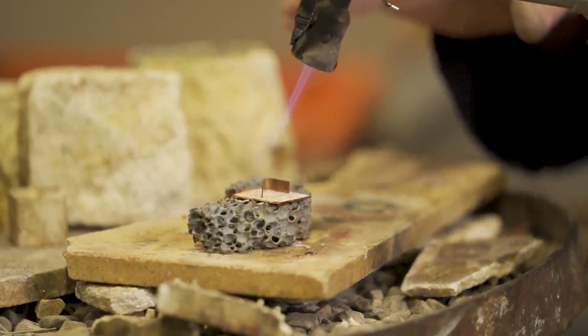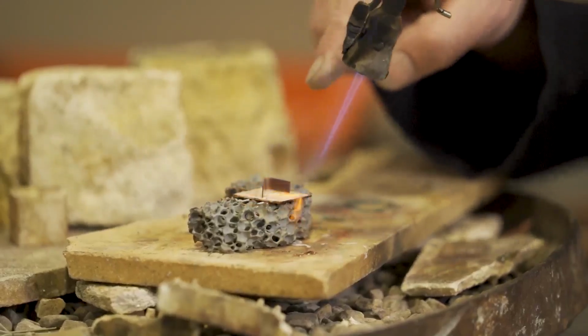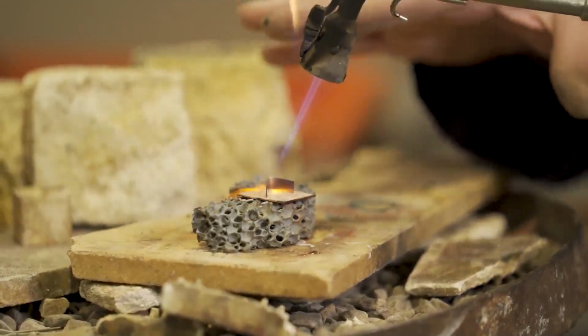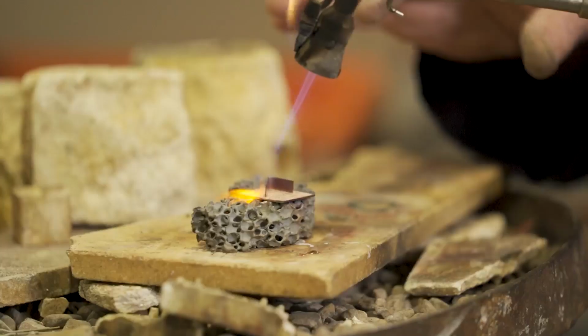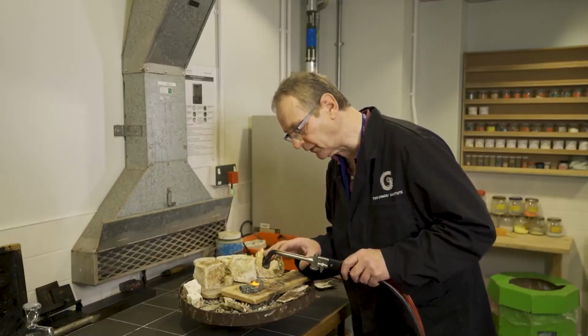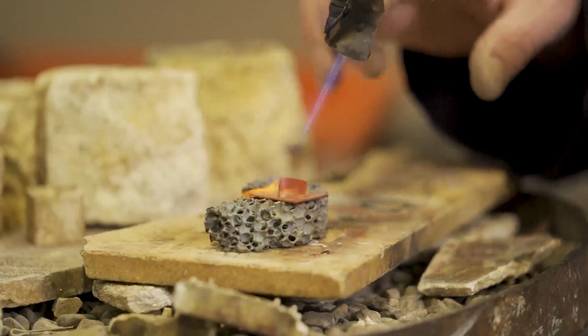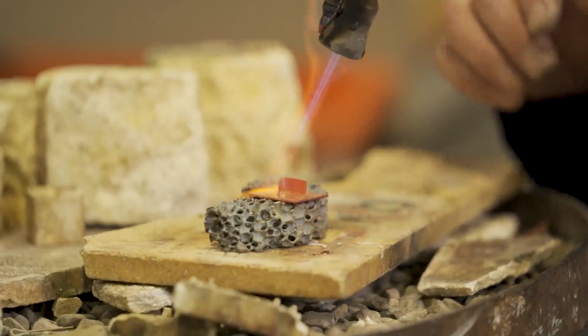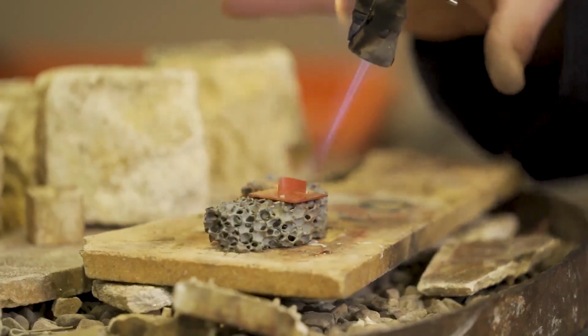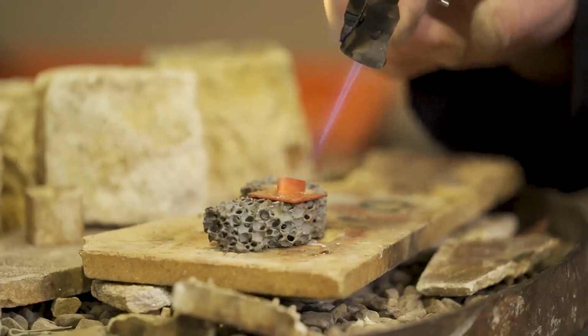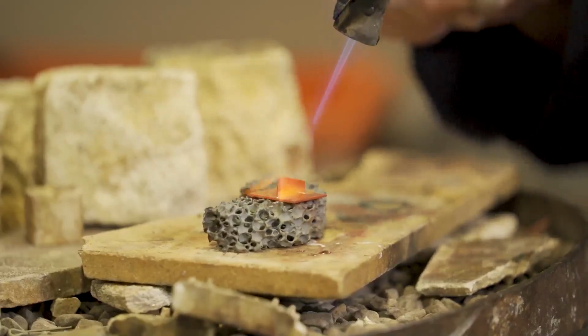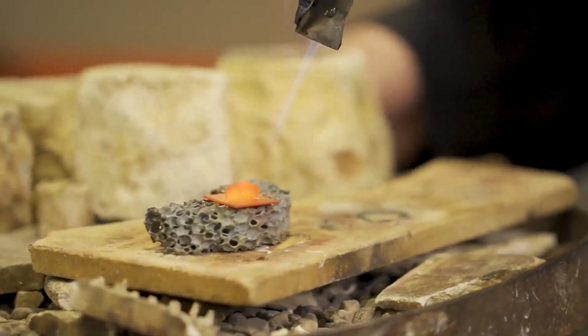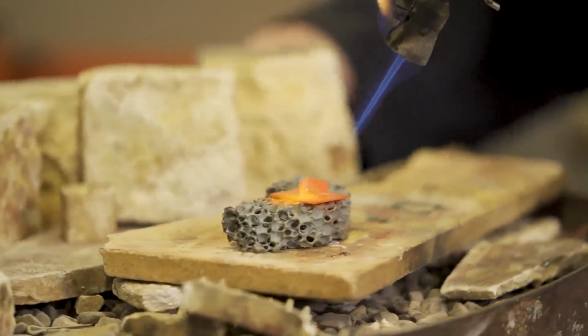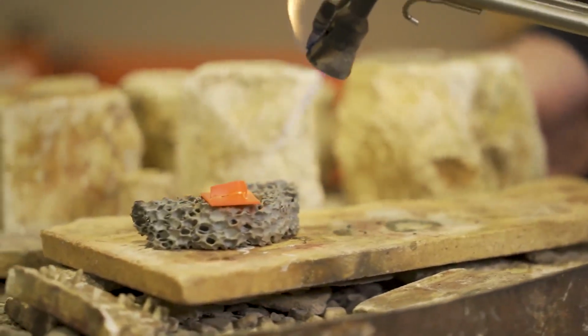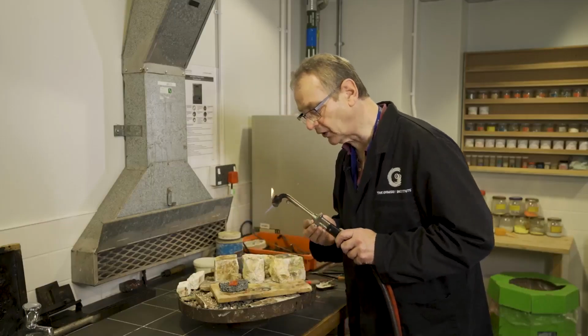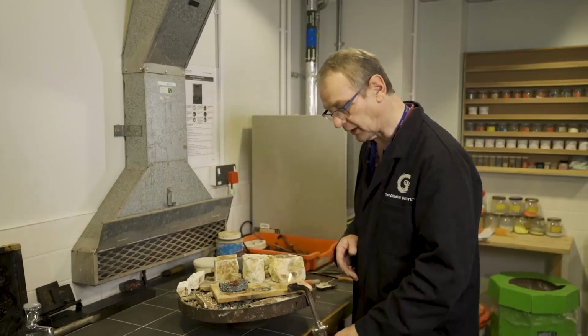So what we've got to do, it's very easy to heat up the wall, so we've got to keep the flame moving so we can heat the base and the wall at the same time. The solder will run to the hottest bit, so if we had the wall too hot, then it would run up the wall. If we had the base too hot, it would run along the base. So we've got to get that happy medium. The solder's got to be touching both bits, and as you see it gets to temperature, you can see the solder running along the seam. And if you can sort of draw it along as well, you can see it shimmering perhaps in the light. Once it's run all the way along the join, then just take the heat off and it'll solidify.